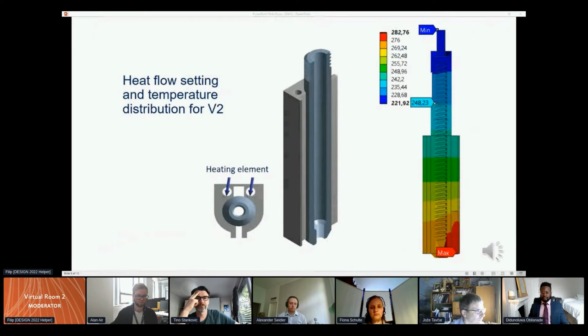We installed two 40 watt heating elements. The casing was covered with a thermal insulation shield, which limited the heat radiation and helped to stabilize the temperature. Finite element method simulations were made with the goal to understand better the dispersion of heat through the assembly. Parts made from stainless steel were compared with aluminum ones.